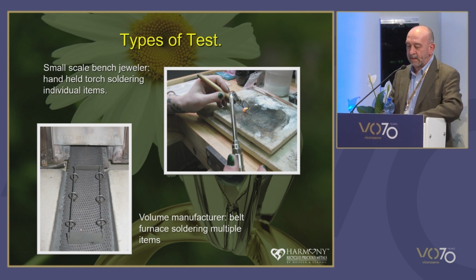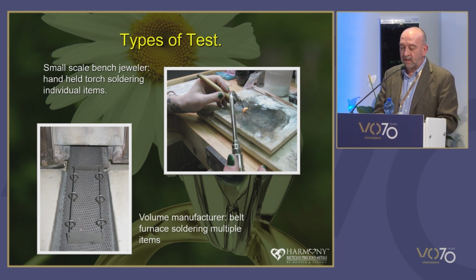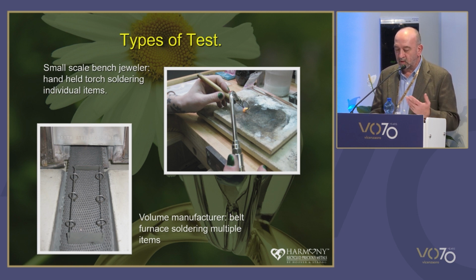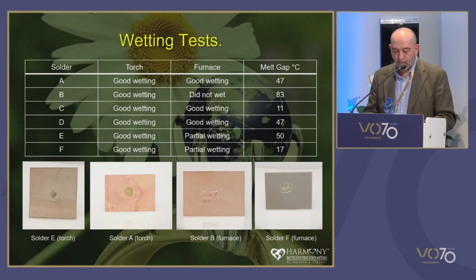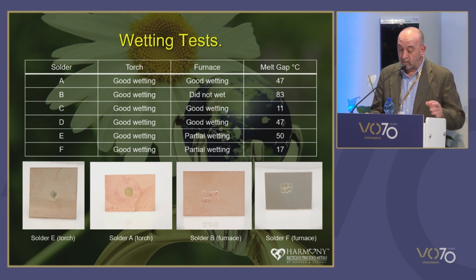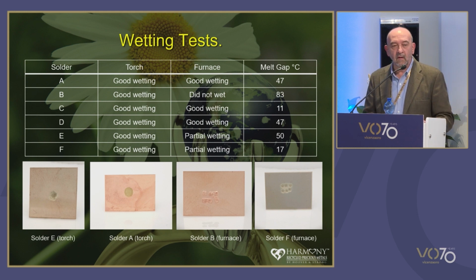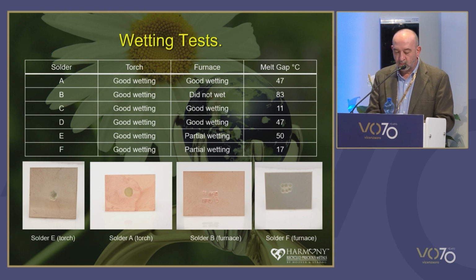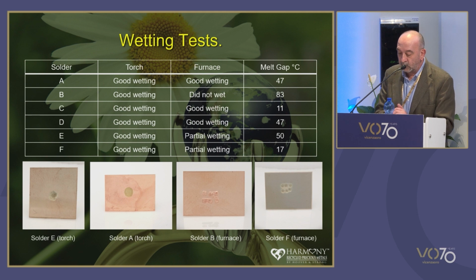And we hoped this approach would highlight any differences in solder performance between the two methods. So the first test we performed was a wetting test. We took 6 pieces of each solder and placed them simply onto a piece of carat gold sheet, and then they were melted using the two methods outlined above. This would give us an indication of how well the solders wet the parent metal under each condition. And as we can see from the results table, the torch soldering tests all showed full liquation, the solders wetted okay, there was no balling, there was no evidence of residual solder left. There did not appear to be any noticeable difference between cadmium and cadmium-free solders.